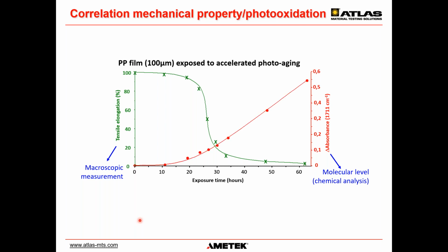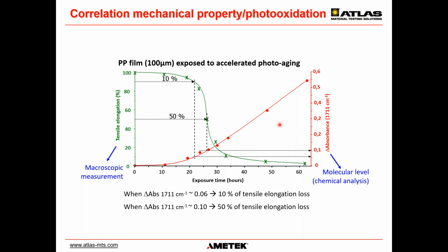And simultaneously, the oxidation rate, the carbonyl index, is increasing with the exposure. Oxidation means the transition, so the oxidation is actually the root cause for the reduction of the tensile strength. So, therefore, there can be a real correlation with relevant data between the different properties, carbonyl index by FTIR, and tensile strength between the polymers. And that's principally a realistic correlation which can be done here.